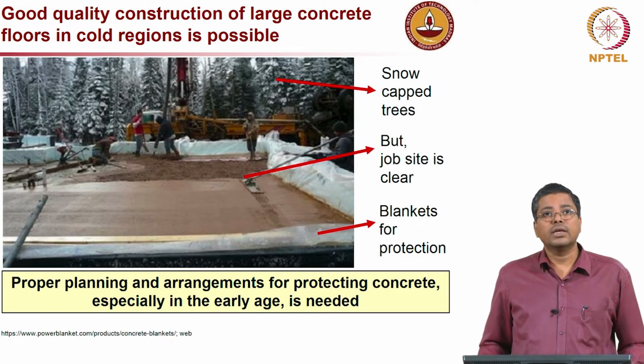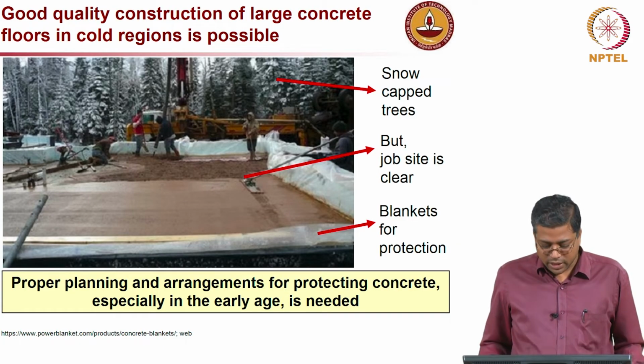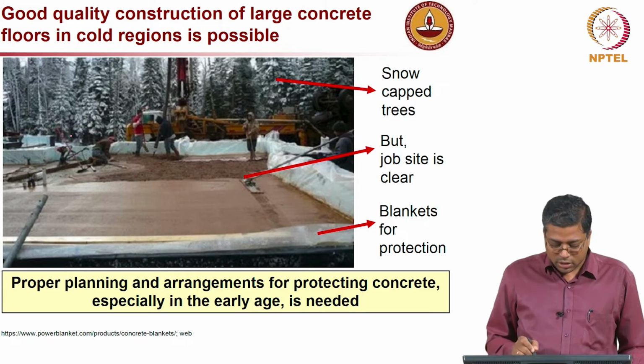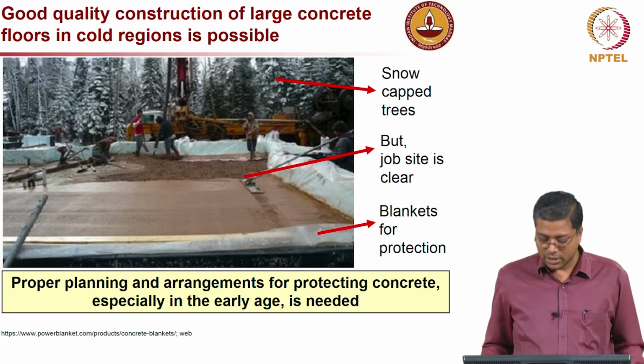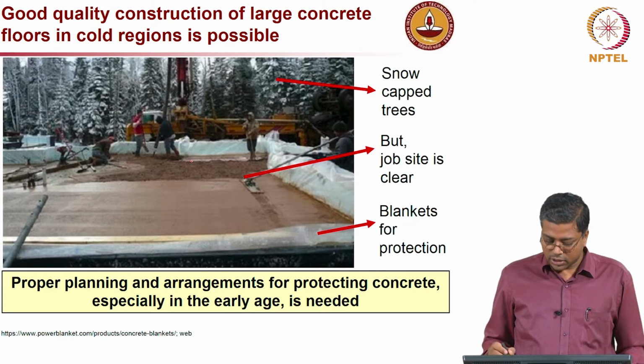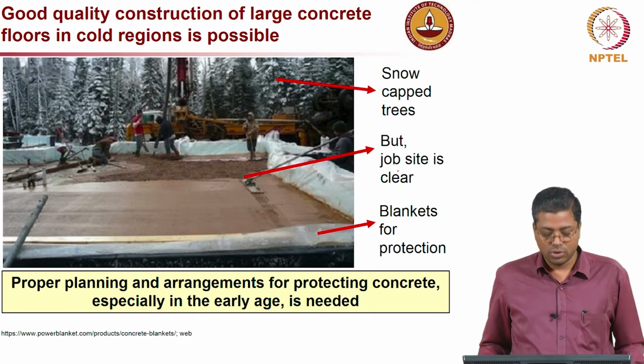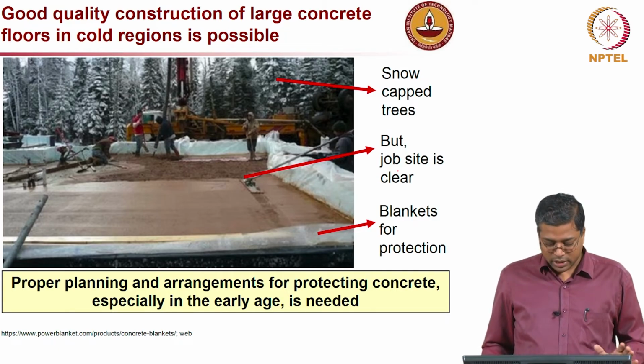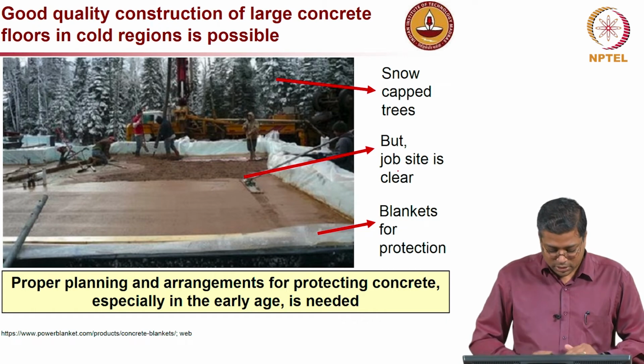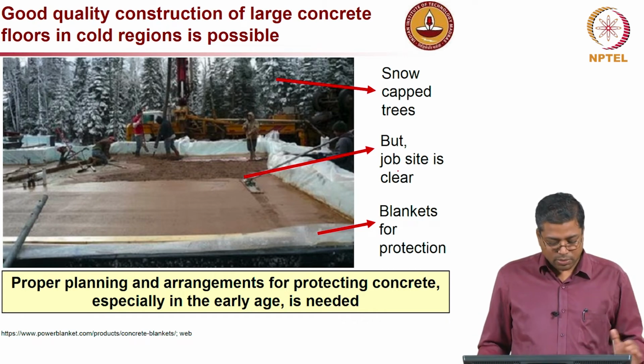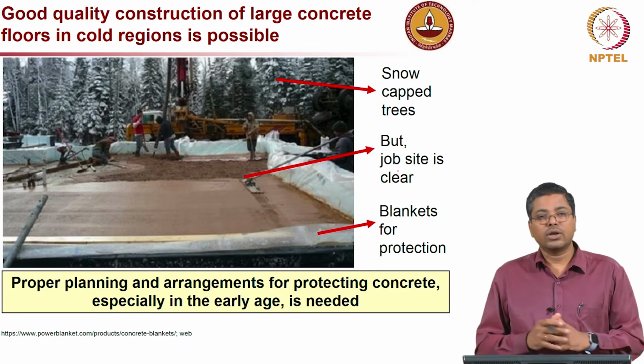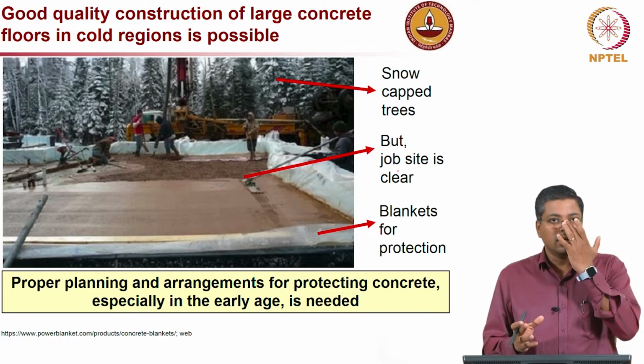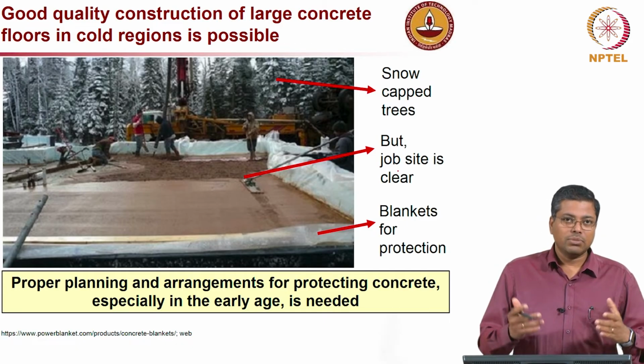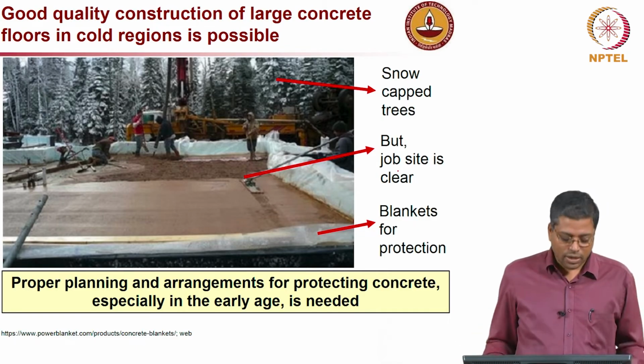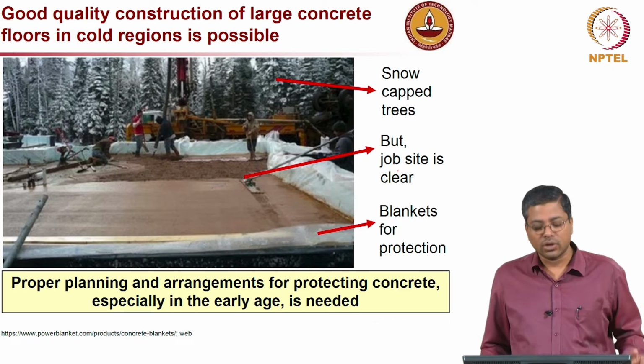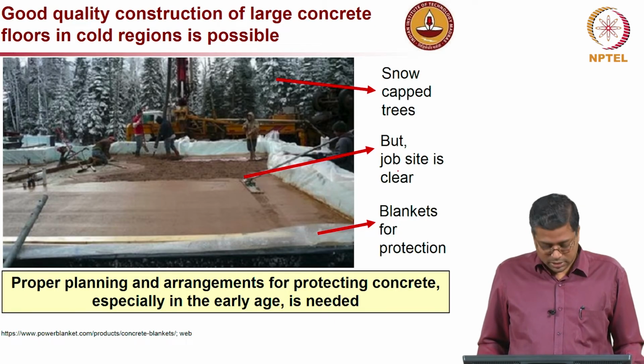So, good quality concrete is possible. This picture very clearly shows that. You can see that all around the concrete slab which is being constructed, you have snow capped region, trees, and the job site, but it is very clear. There is no snow on the concrete surface, and the concrete is well protected. In this picture that's plastic sheet which you see around, and also the blanket, it is going to keep the concrete well protected from losing the heat which is generated because of the exothermic reactions, and at the same time the immediate environment of the concrete can be maintained at a reasonably high temperature.